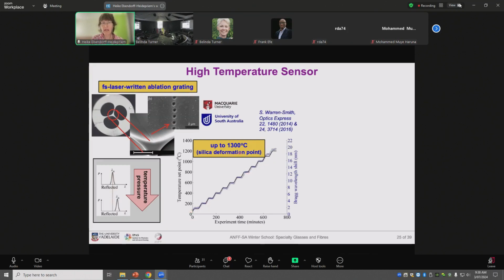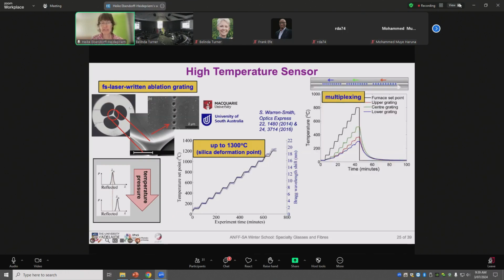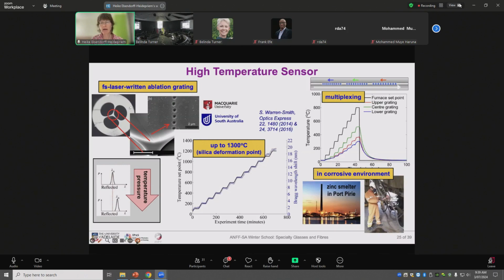And so monitoring the wavelength of the back reflected light allows us to do the temperature sensing, which is shown here. Because everything is single material, the fiber and the grating, we can go up to the silica deformation point, which is 1300 degrees Celsius for short-term sensing, 1,200 for longer-term sensing. Several gratings can be written in one fiber, and this then allows multiplexing. Again, I would like to mention a startup company, HD Sensing, and they embedded this type of fiber sensing in a furnace that has been used for a zinc smelter at the Port Pirie Nyrstar facility.